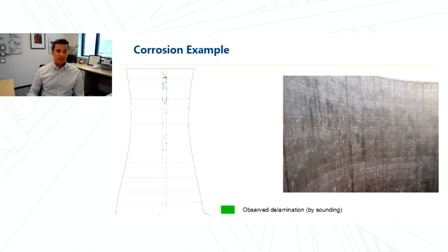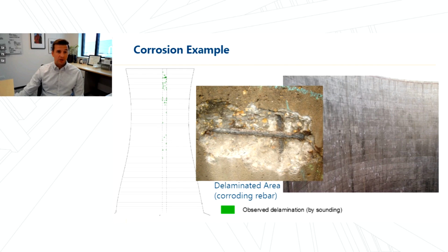This is the interior surface of a cooling tower with exposure to brackish water. There's very little visual evidence of corrosion damage in this right-hand image. We see a little bit of efflorescent staining, but there's no spalling, there's no widespread cracking. But hands-on methods like hammer sounding identified delaminations, that subsurface cracking that we're concerned about. The image on the left here shows a swing stage drop about 20 feet wide, and the green areas are those that were identified to be delaminated using hammer sounding techniques. And then we also used inspection windows to confirm that there is a corroding reinforcing bar with consumption of the steel area of that bar.